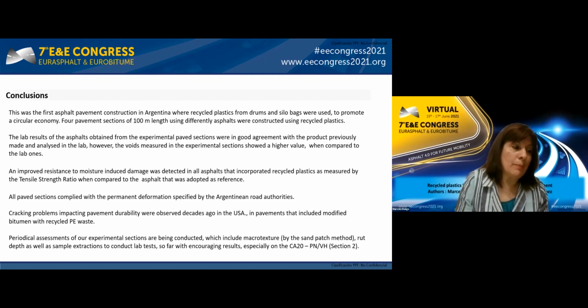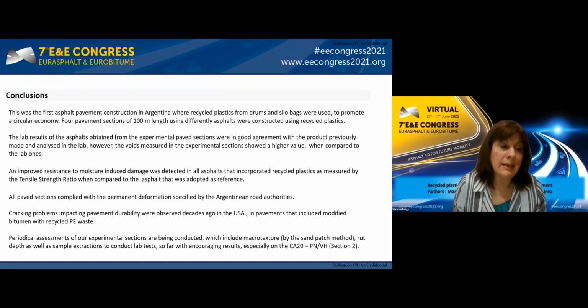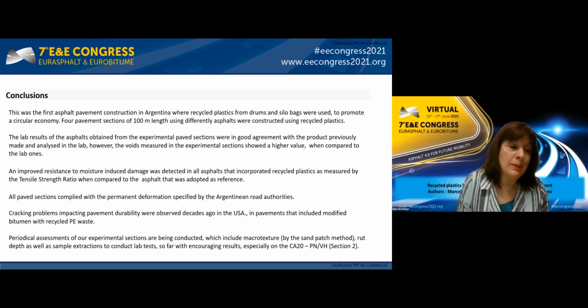Thirdly, all paved sections complied with the permanent deformation specified by the Argentinian road authorities. Fourthly, while cracking problems had been observed decades ago in the USA in pavement that included modified bitumen with recycled PE waste, our periodic assessment of our experimental sections, which includes macrotexture analysis by the sand patch method, rut depth assessment, as well as sample extraction, so far has given positive results, especially on the CA20 – PN/VH asphalt mix used in section 2.